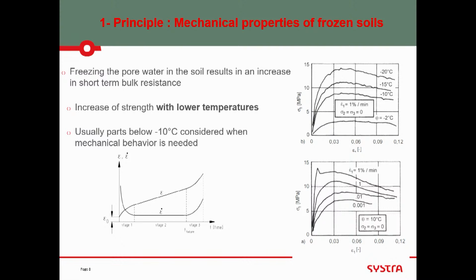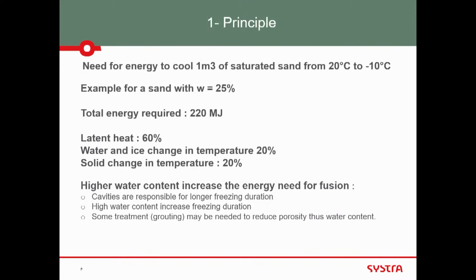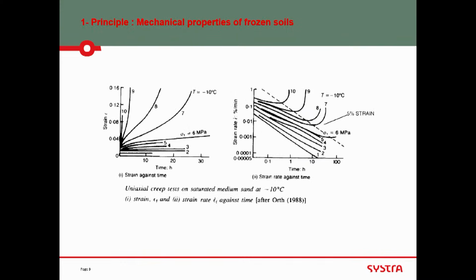So in laboratory, when we test the soil, in fact, we try to define this slope, this epsilon dot, because if we don't load it a lot, if we load very slightly the sample, in fact, it doesn't reach the critical strength, and in this case, it's stable. But in this case, you need a very thick frozen area to resist the weight of water and soil, which applies under the annulus, for example, in a cross passage. If you load it quickly, or if you load it to 6 MPa, for example, it will diverge.